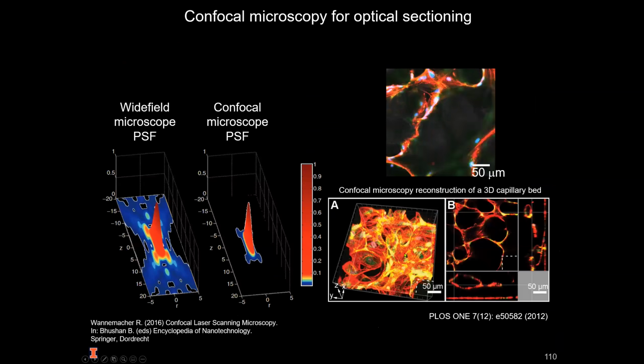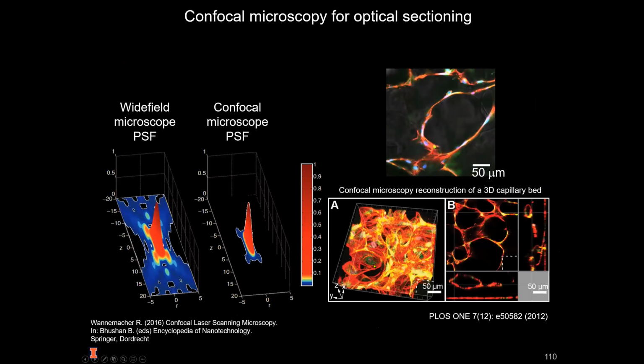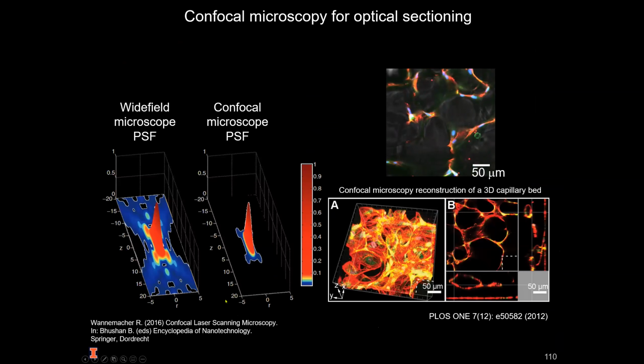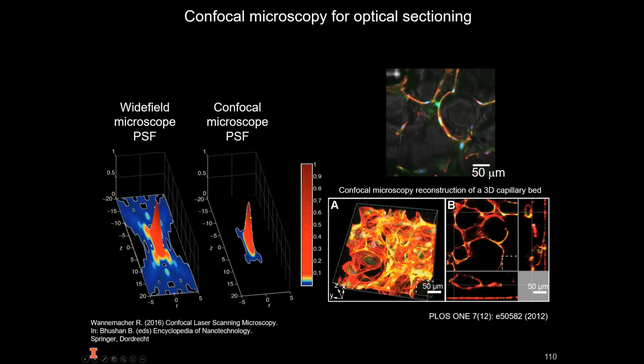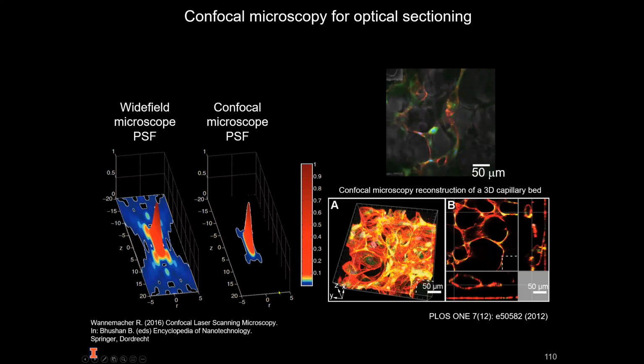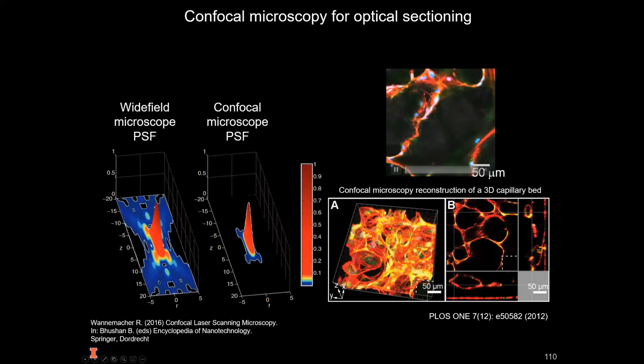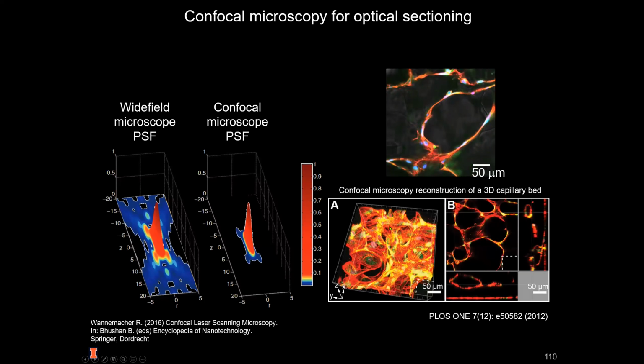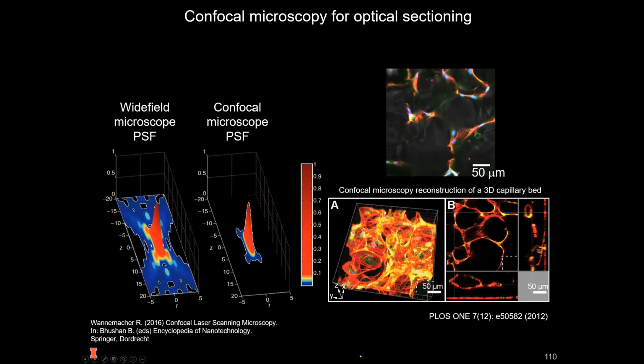By adding the pinhole, we get clearer images, and because the point spread function of the confocal microscope is much more concentrated than the wide field microscope, especially in the axial direction, its depth of field is much reduced. That makes the confocal microscope ideal for optical sectioning, where we collect a series of images at different focus positions to map the volume of our sample.